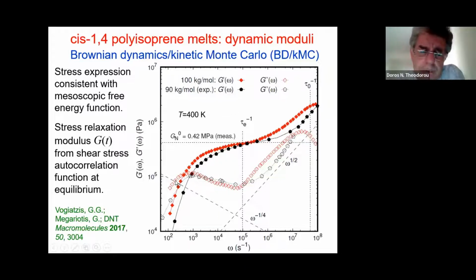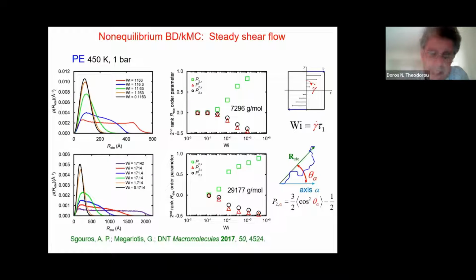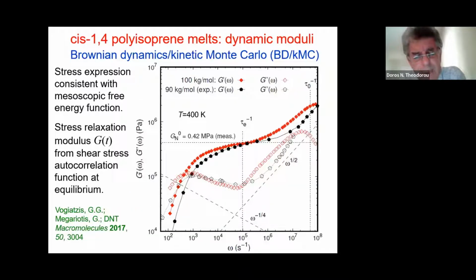And it is being compared with experimental measurements for this polymer, which is cis-1,4 polyisoprene, essentially natural rubber, uncross-linked. And we see a pretty good agreement for relatively close molecular weights. Of course, this is a very strong function of the molecular weight. What is particularly gratifying is that we can calculate these moduli at low frequencies.